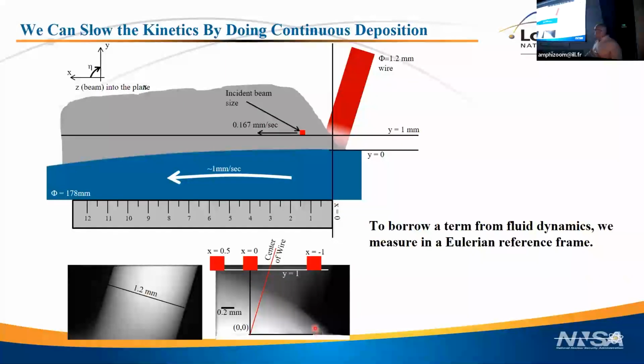And here you can see the contact angle of the liquid on the solid substrate. And this is what our beam size looked like relative to all these things. This is relatively to scale. So what we did is we sat the beam here and collected data while material flowed past it, right? So this is, to borrow a term from fluid dynamics, we measured this in a Eulerian reference frame. So we watched particles as they flow by here. That essentially gives us infinite time resolution, right? We can sit here and count all we want because, well, once it's reached steady state. So we can now look at this with much better time resolution.